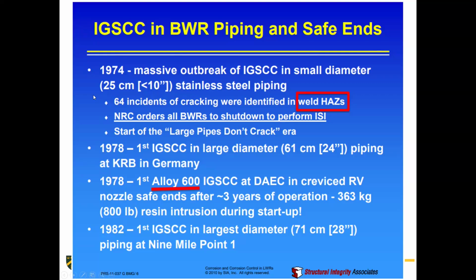All right, so let's go over a little bit of history here, because I think this helps to put things in perspective for what's gone on historically. Prior to 1974, there were some issues with this kind of phenomenon. But they were primarily driven either by contaminants, which were pretty obvious, or the fuel cladding itself. Back in the day, instead of using zircaloy, we were using stainless steel, and that had some problems as fuel cladding. But whatever. Starting in 1974, though, we started to see a phenomenon within the worldwide fleet of BWRs, which was this intergranular stress corrosion cracking. Initially, this was showing up just in these narrow feed channels, this narrow piping.